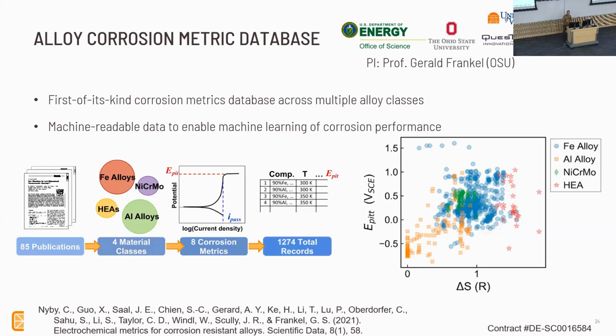And the plot on the right is basically a summary of the data points, color-coded by what alloy class they are. And on the y-axis is one of these corrosion metrics, the pitting potential. So it's the amount of electronic potential across the material in order to induce a pit within the surface of the material. And the x-axis is configurational entropy of the formula, which was meant to indicate how simple the alloy is versus how complex it is, because high entropy alloys, or HEAs, is one very common hot topic right now